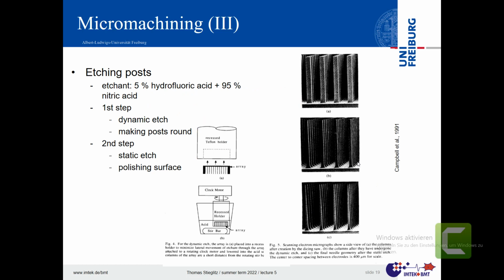And then everything is put into a very aggressive etch. Hydrofluoric acid, HF, is the most aggressive etching agent you can imagine, and nitric acid. By that you round up the square-shaped posts. Those square-shaped posts have corners, and the more cornerish something is, the more aggressive are etchants or electrical fields, so we round that up. And if we do some tricks with inclination and moving things, we can even etch them thinner at the tip. For that, we have semiconductor material needles standing around, having neither a metal interface nor an insulation.